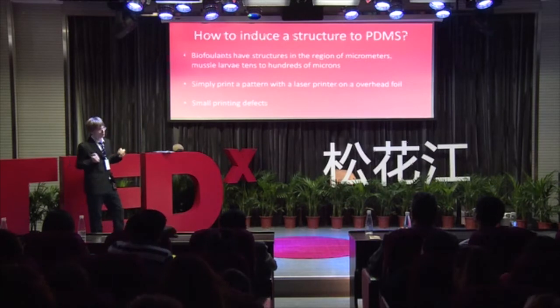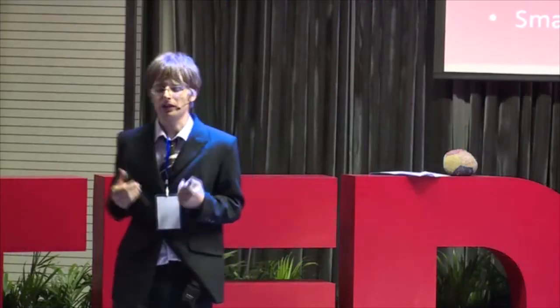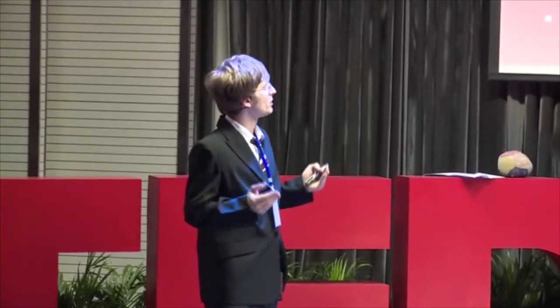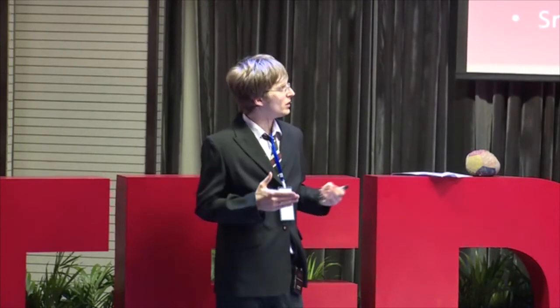So there's a big problem with this surface area minimization until now, because every biofoulant has a different size. Mussel larvae are around 100 times bigger than bacteria, and if you want to prevent bacteria and larva settlement at the same time, you need to have a structure on top of a structure, which is called a superstructure.